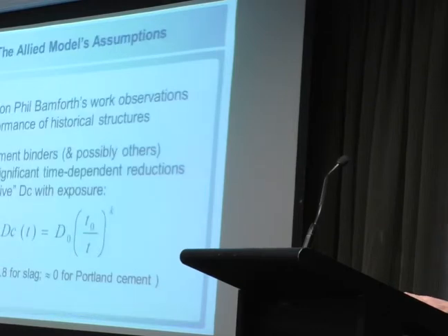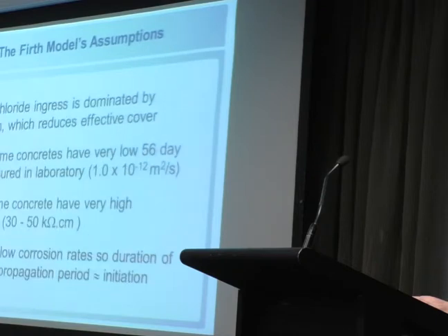So the Allied model, which was one of the concrete industry players, is based on work produced by Phil Bamforth in the UK of Taywood Engineering. And the crux of it was a claim that if you look at historical structures, you see a reduction in the apparent diffusion coefficient over time. So your concrete progressively becomes more resistant to penetration of chloride ions, and that reduction is very large for concretes containing slag binders and virtually zero for just binders with plain Portland cement. By contrast, the Firth model was somewhat different. It was less empirical.